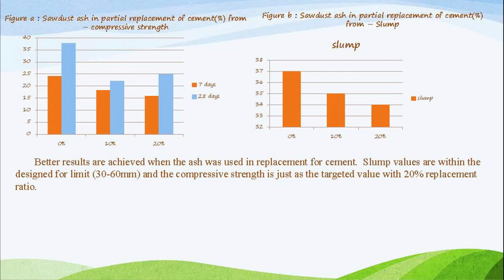The workability, or slump test, of the sample using sawdust decreases by about 20%. Then if we increase the percentage of sawdust used in replacement of cement, the workability also decreases. Better results are achieved when the ash was used in replacement of cement. Slump values are within the design limit of 30 to 60 millimeters, and compressive strength is just at the target value within a 20% replacement ratio.